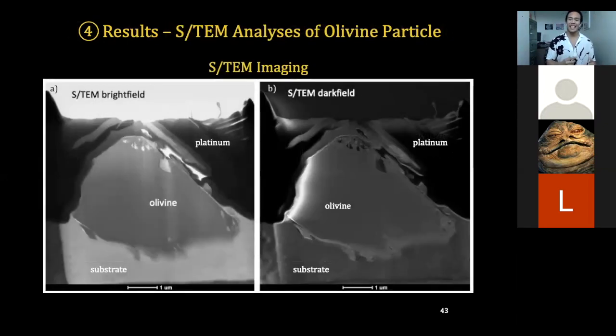So moving on to the STEM analysis of the thin section that we created. This is a STEM bright field and STEM dark field image of that olivine-like particle where we created a thin section. The center of both of those images is the actual particle. The top darker region is the platinum protective cover that we put down during the milling process. And then the bottom is the substrate where the particle is attached.